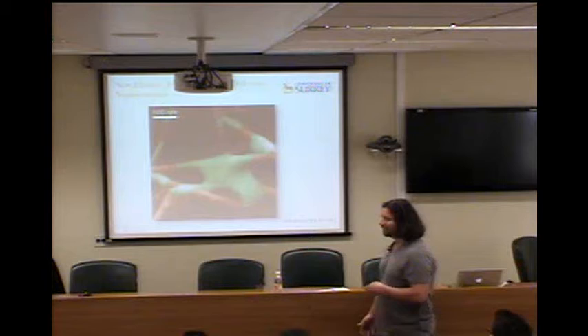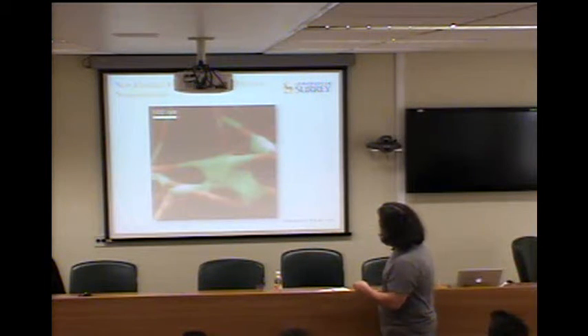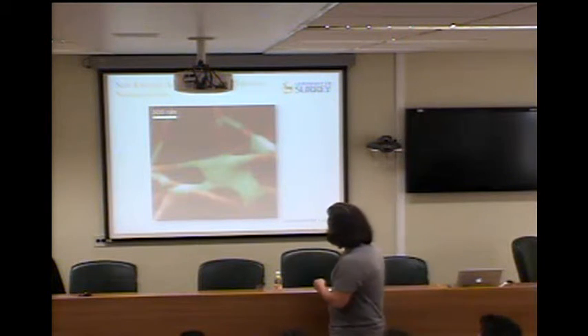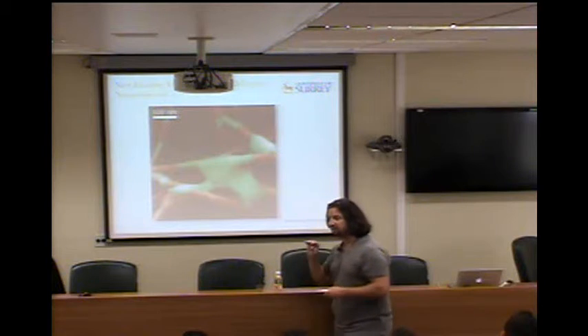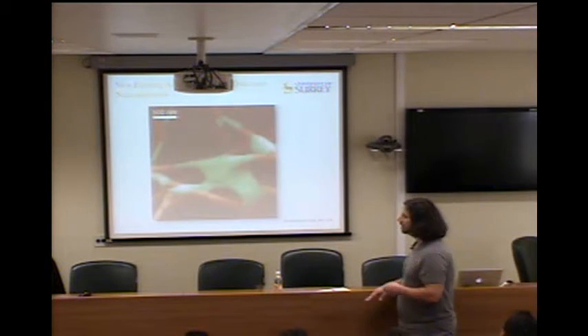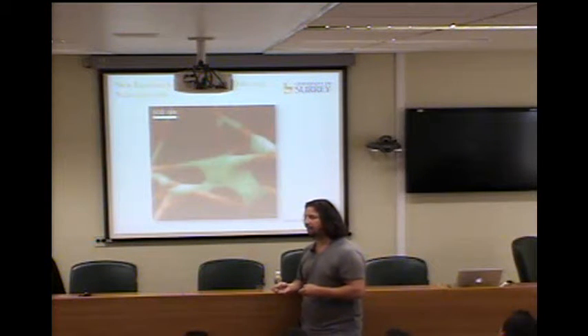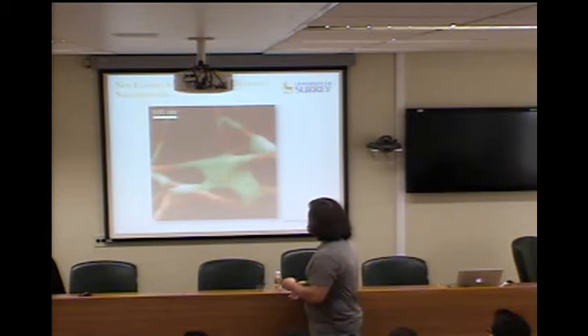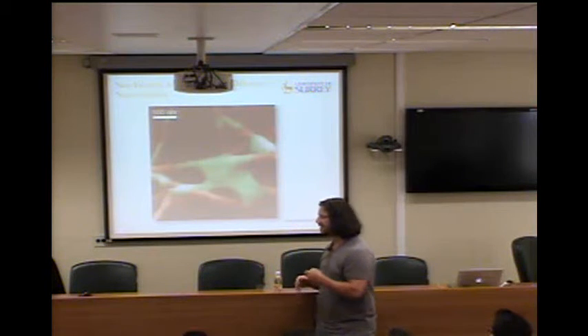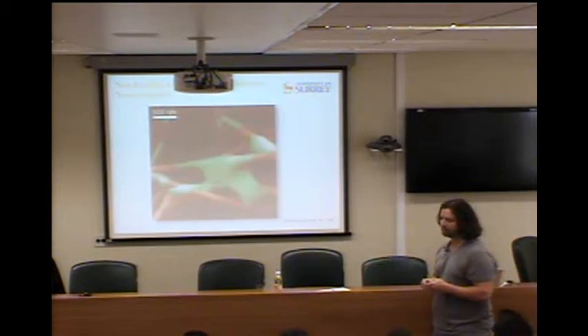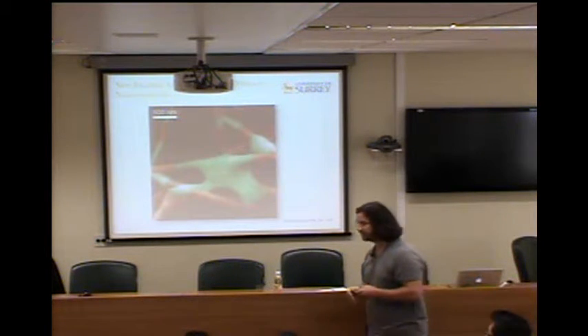So what we've been doing is putting so-called graphene blankets down at these interfaces. The red stuff is silver nanowires, and the green stuff is this graphene stuff that we spray down, and because the surface energies are quite similar, it attaches itself at junctions, and basically reduces the contact resistance. So with these types of materials, you have a very cheap, very flexible material that has better properties than ITO. Okay, so I'm not sure whether this is the future of touchscreen displays, but it's definitely a first step on the journey to producing materials that we can use as replacements for ITO. And so Antonio won't have to throw away his iPad.